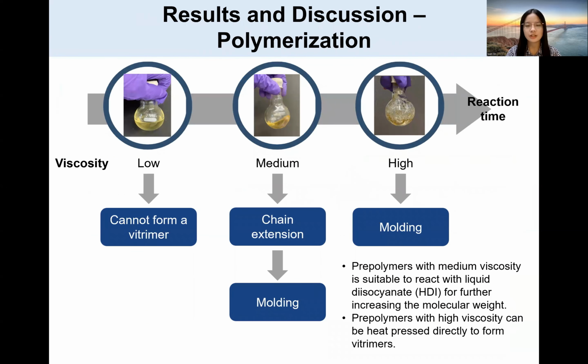During polymerization, the mixture slowly changes from being fluid, viscous to glassy. In some cases, the viscous mixture, which is the mixture of medium viscosity, will further undergo chain extension to increase the molecular weight. And after chain extension, the prepolymers will gradually become glassy, and lastly, only the glassy prepolymers will be taken to heat press and form themselves as vitrimers.